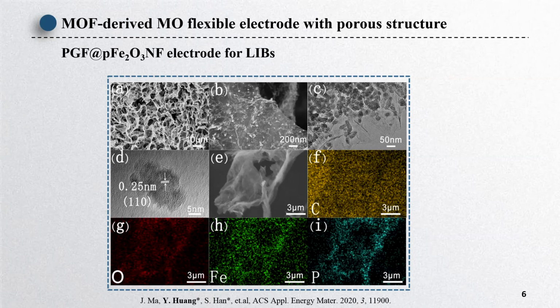The morphology of the composite was characterized by SEM and TEM images. From SEM, we can find the composite has a 3D structure, and both SEM and TEM images showed that the ferric oxide particles were homogeneously dispersed on the graphene surface. The high-resolution TEM showed that the crystal lattice spacing of the particles is 0.25 nanometers, which corresponds to the 110 planes of alpha ferric oxide. The SEM mapping showed that carbon, oxygen, iron, and phosphorus were homogeneously dispersed in the composite.